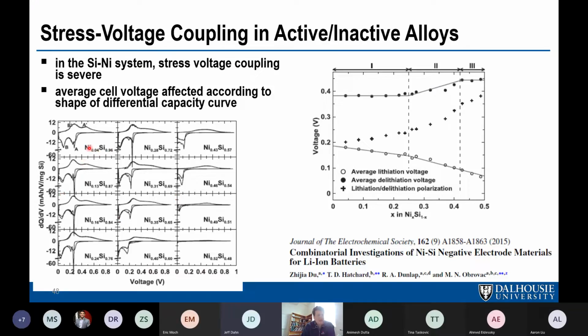And if you use nickel alloyed with silicon as an alloy, it especially shifts the voltage curve compared to other transition metals. Some transition metals don't shift it at all, some shift it a little bit, and nickel shifts it a lot. And it seems to be related to the binding force with silicon. And so here's the differential capacity curve of silicon with a little bit of nickel in it. It's enough to suppress the Li15Si4 phase completely.